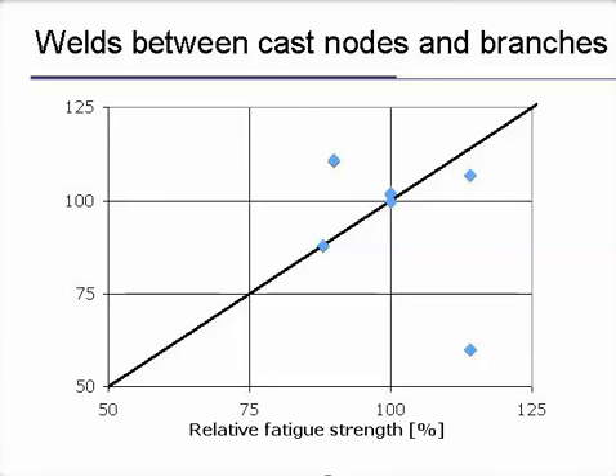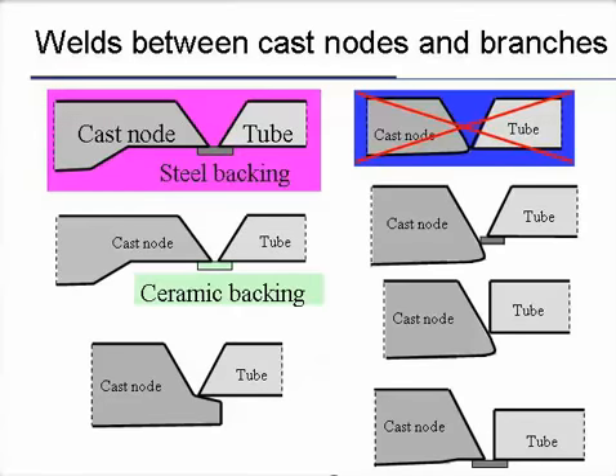And we can see here when we compare relative fatigue strength and relative fabrication cost, this is this solution. So funny, but still interesting, because then it means that you can effectively do a good job. Of course, you have to ensure that you have a good penetration here at the root. But once you do this, then you can have a very good resistance. Last but not least, the solution here is even better, because then you have an eccentricity that goes in the right direction and you put compression here into the root. That's the solution that's used in the offshore industry, but in steel construction, often architects prefer this one because from the outside you don't see the difference between the cast node and the rest of the structure.